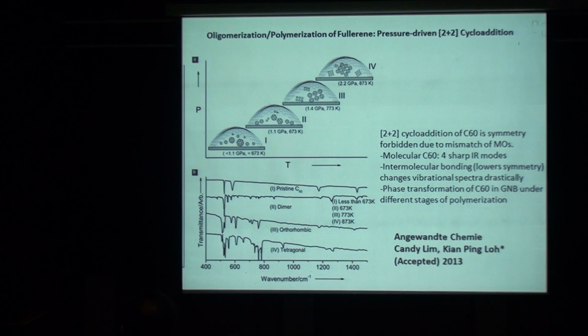Oligomerization, or what we call the polymerization of these C60 molecules, you can track using, again, FTIR. Pristine C60 molecules, because they are highly symmetrical, show 4 peaks. The moment you put it inside the bubble and start heating up, new peaks appear, which we can assign to the various different phases because of the oligomerization of these C60 molecules to become a dimer, tetramer, and so on. And the phase transition is very sharp. From 1 C60 to 2 C60 to 3 C60 joining up, it's a very sharp phase transition.